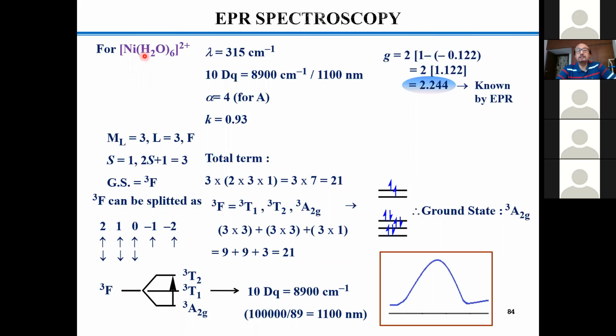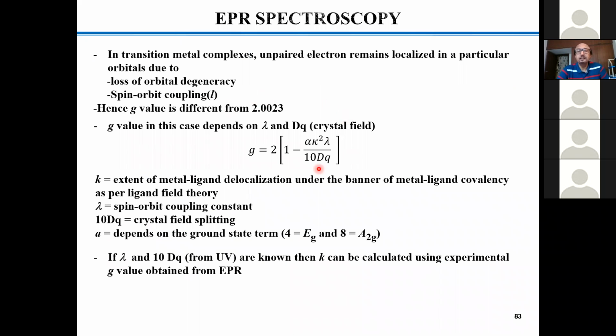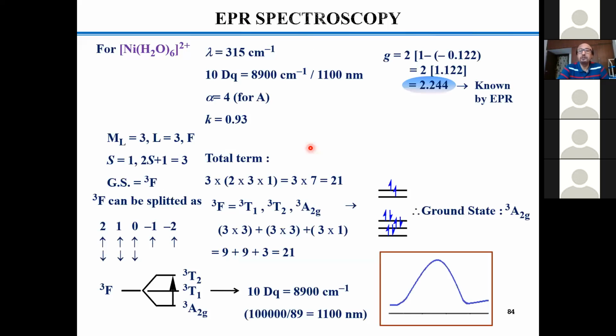Nickel 2 octahedral geometry, lambda is known from the book, and the ground state is A, alpha is 4. Okay, so if you put that in the equation, 10 DQ known, lambda known, alpha known, and g is already known. g is 2.24, and then you will get the K value. Am I right? So 2.24, you can see it, 100% metal based. That's no debate, no doubt over here.